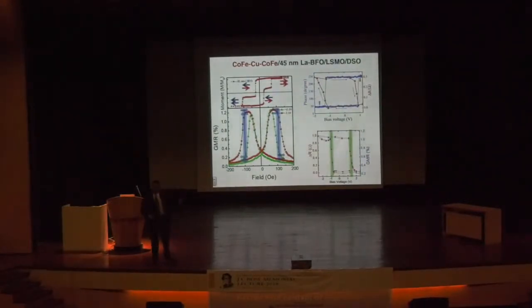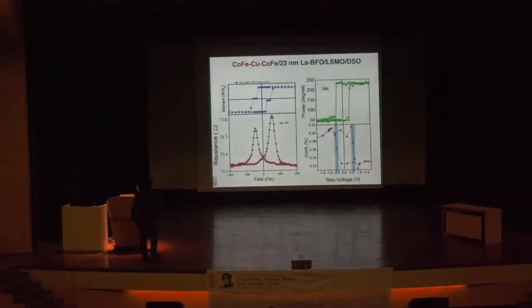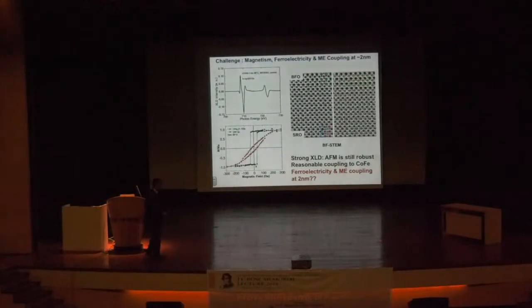If I go by another 50% down in thickness, this is 23 nanometers, that voltage goes down to 0.5 volt. So we're in the process of looking at 10 nanometers and 5 nanometers of the multiferroic. The question is, what happens to the coupling? Are these materials the same as a macroscopic material, or is it very different? And we're still trying to probe that. One of the ways to probe it is to directly image the order parameters.